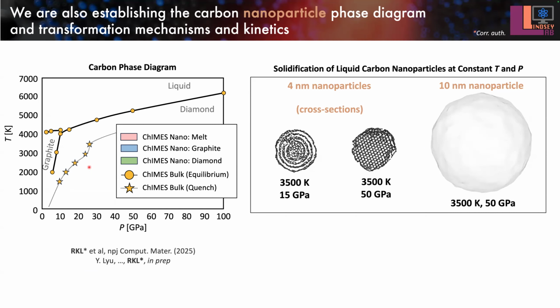This went through a little bit quickly. I'll just go back so you can watch this again. What we're looking at here are two different particles — cross sections, 4 nanometer nanoparticles. We're cooking them at 3,500 Kelvin and either 15 or 50 gigapascals.